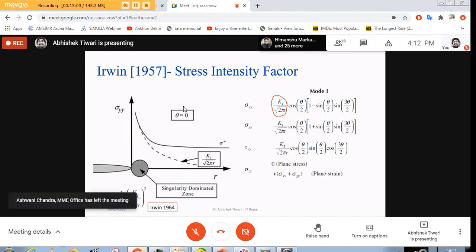And he calls this one, which is actually sigma root pi a, and this is what we saw as a signal in Griffith's analysis, a stress intensity factor. It is called a stress intensity factor because by this much amount, the stress is being intensified. The other important parameter is r. When you approach closer to the crack tip, r will be 0 somewhere here. When you go closer to the crack tip, the stress goes to infinity.